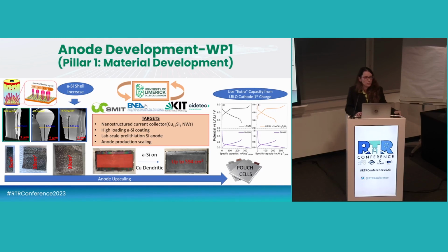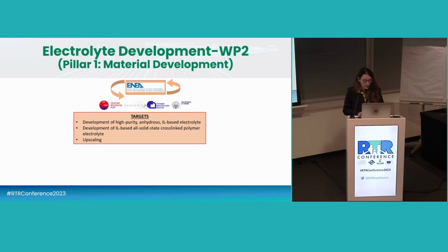The strategies that we are using for this kind of chemistry are how we can tackle the very big problem we are having, that is the very strong capacity loss, especially when we are using a silicon-based anode. And the strategy is to use the lithium-rich cathode that compensates the capacity loss that we are having at the anode for the first discharge.